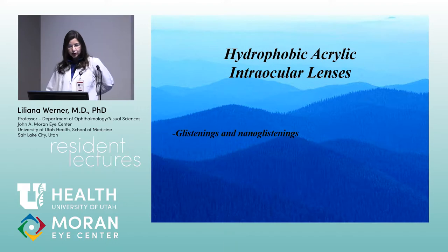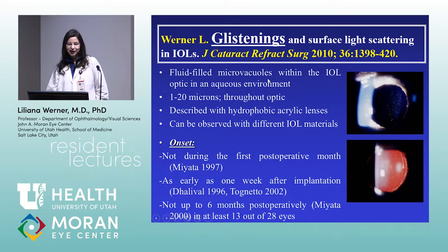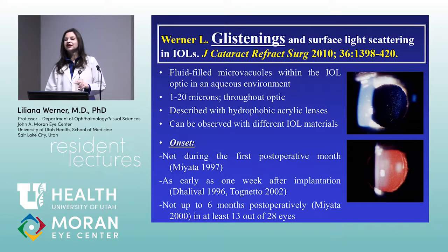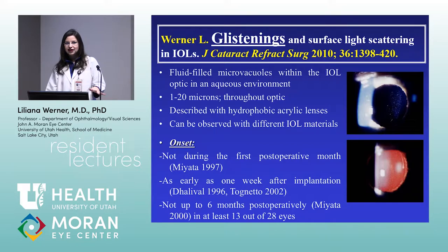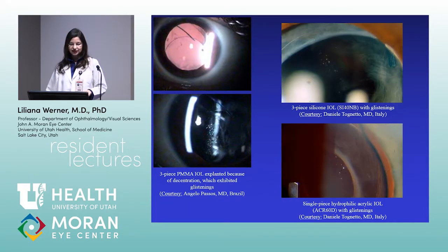Hydrophobic acrylic lenses have two main issues: glistenings and subsurface nano-glistenings. Glistenings are fluid-filled micro-vacuoles within the IOL in an aqueous environment, generally up to 20 microns in size. They are mostly described with hydrophobic acrylic lenses, but can occur with any lens. Not all hydrophobic acrylic lenses are equally affected — one specific material is more problematic. With the AcrySof lens by Alcon, if you carefully examine at the slit lamp, you will essentially always see glistenings — even in small amounts — sometimes as early as one week after surgery.